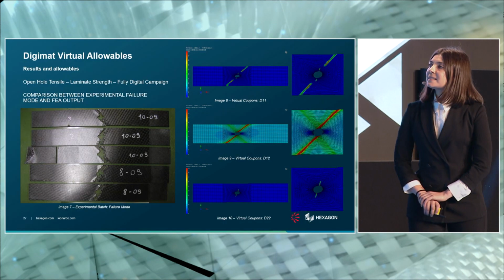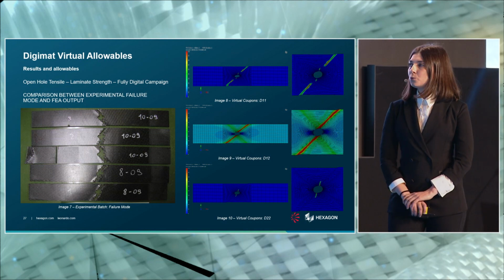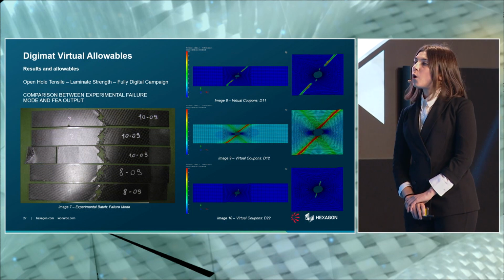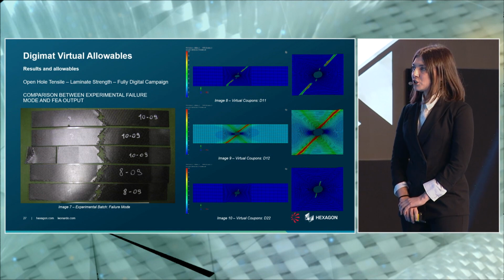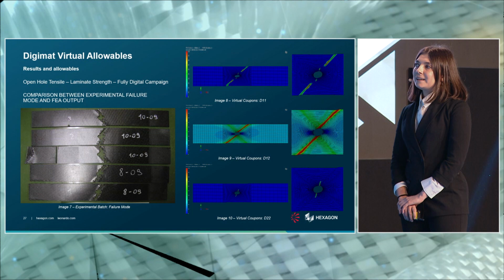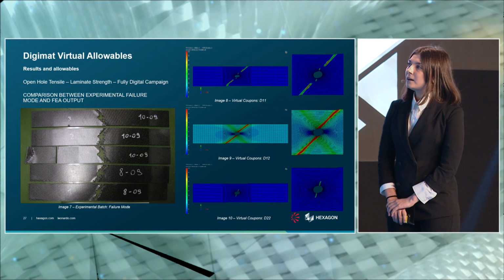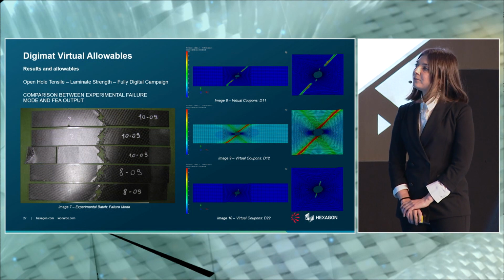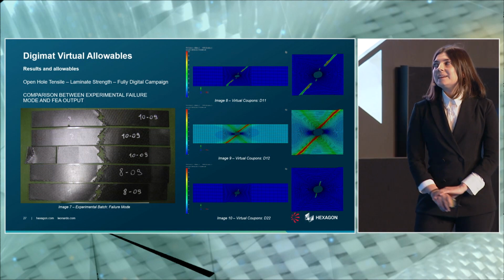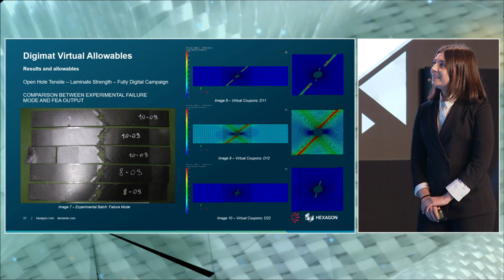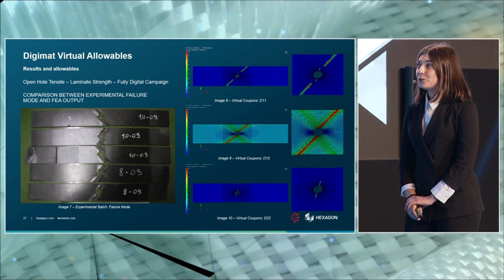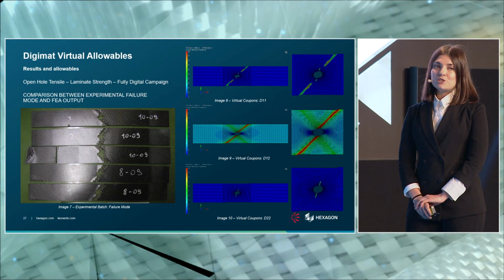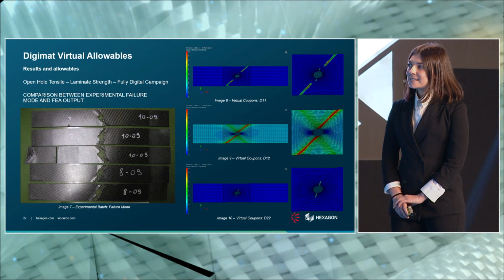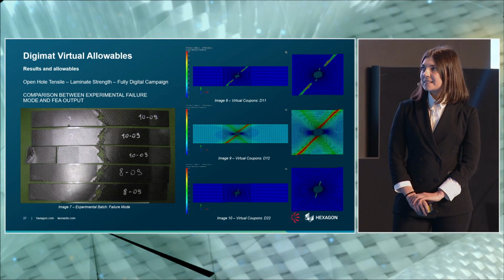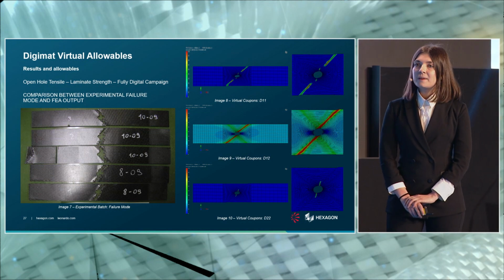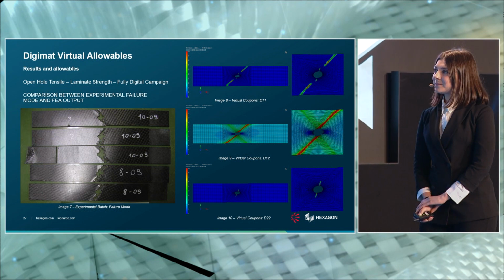Then, this is a comparison between the failure mode of the experimental batch. As we can see, the failure is at 45 degrees from the hole. And on the right side, we have the FEA analysis output in terms of damage components. And as we can see, we reached the same failure mode in the experimental and in the virtual analysis.